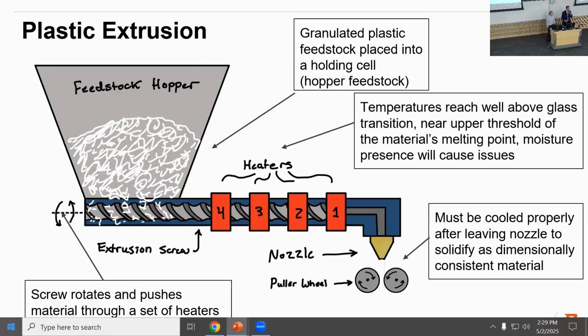This is a part where you really do not want any excess moisture, as any moisture will likely boil, pop, and cause the integrity of your filament to be weakened. And on top of this, there must be a proper cooling method between the extrusion at the nozzle and the puller wheel so that it's not flattened by the puller wheel when it gets there.